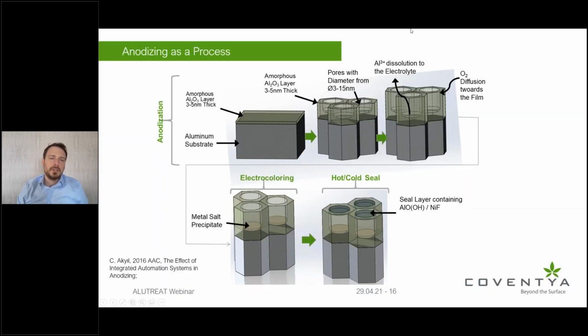We briefly mentioned it, but the textbook definition of anodizing is growing or converting the inherent oxide film, which is present on the surface, by applying an anodic polarization on the surface into a porous, transparent, nanostructured media, as you can see here. And this structure is actually one of the hardest materials in the world, and making it transparent is actually converting the surface, better expressed, to a much more durable form.